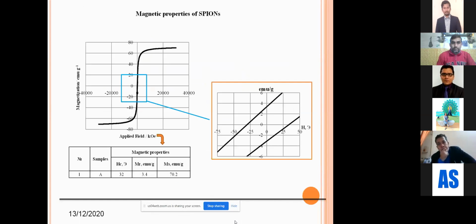So this is one of the important parameters I told you about. What is the difference between magnetite and superparamagnetic iron oxide nanoparticle? In the presence of an external magnetic field, it holds a single direction, and should work as a magnet. So here we are able to see the saturation magnetization, remanence and coercivity of the magnetic nanomaterial, and could see that the nanoparticle showed a maximum saturation magnetization of around 70.2 emu per gram, and that is the advantage.